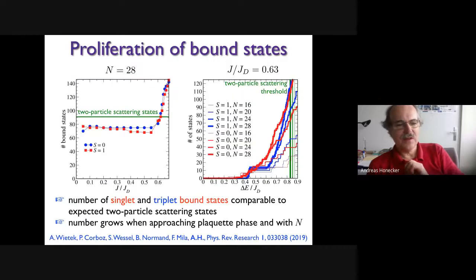Okay, here is a bit more detail on the number of bound states that you get below the two-particle scattering states. Here on the left is one system size, and you see that the number of bound states is actually starting to even exceed the number of scattering states as you go very close to the phase transition. And here on the right is the parameter ratio relevant to strontium copper borate, as a function of system size. You see that if you go to bigger systems, you get more singlet bound states. You also get triplet bound states, but you get more singlets. So the number of bound states below the two-particle scattering threshold grows with system size.